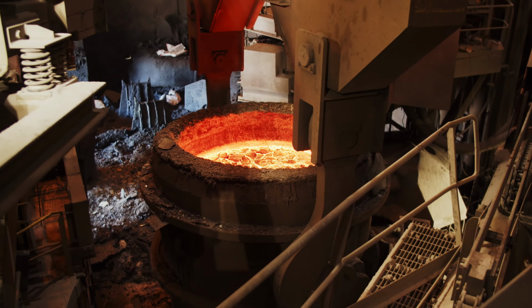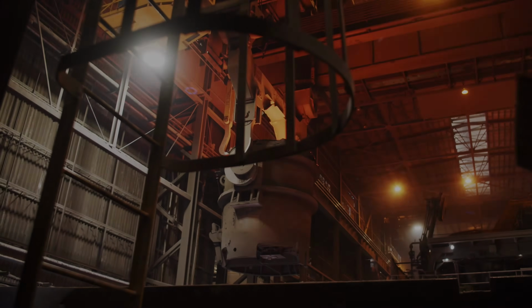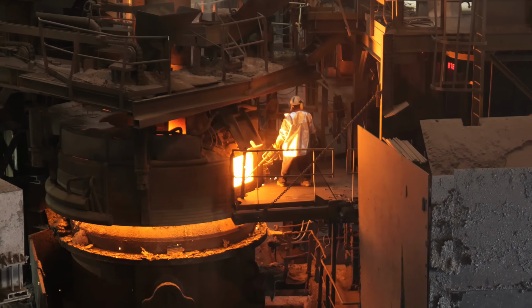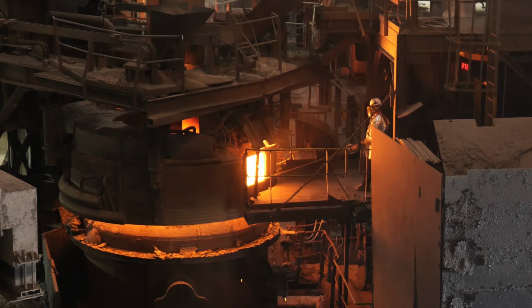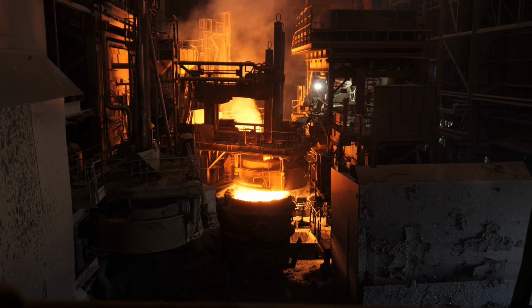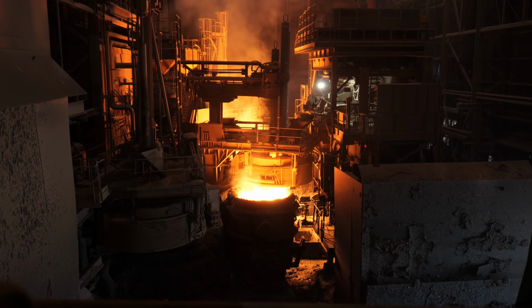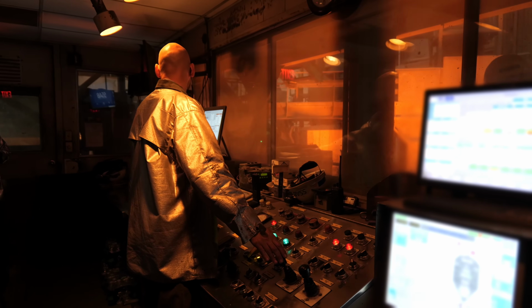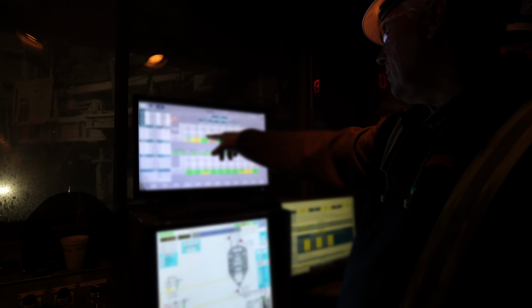The crane will pick it up, it'll take it over to the ladle metallurgy furnace we call the LMF, and then the operator will hook up their argon lines so they can stir the vessel, the ladle, and then they'll take a sample so they can get the chemistry of the steel. And with that sample analyzed at the chem lab and transmitted to them, they can see what the composition is at, and then the recipe for the grade of steel that we're going to make on the screen in front of them.